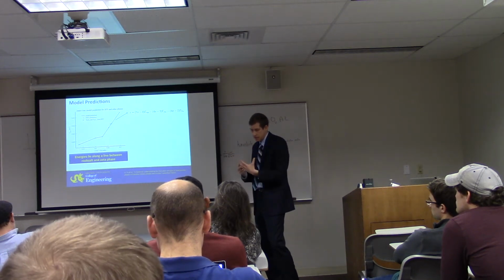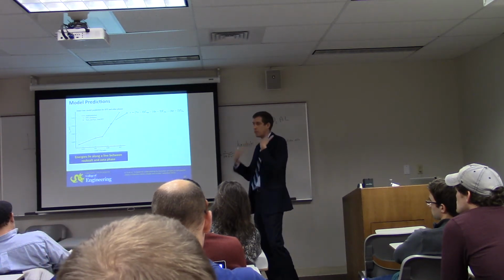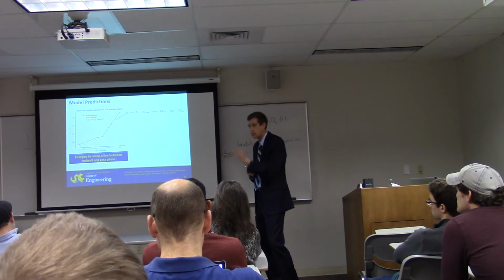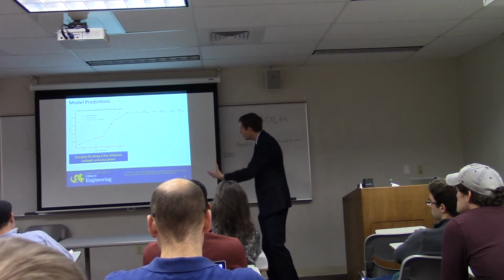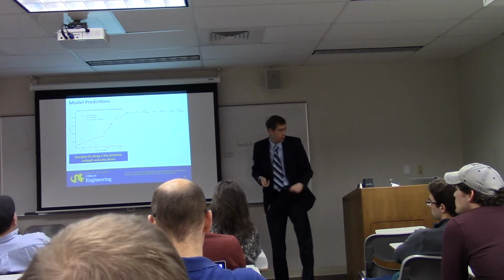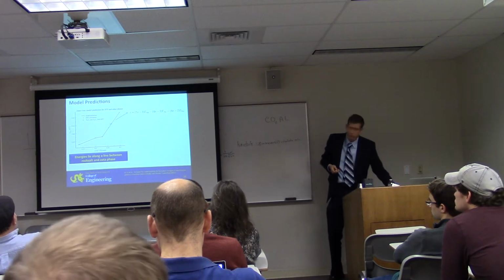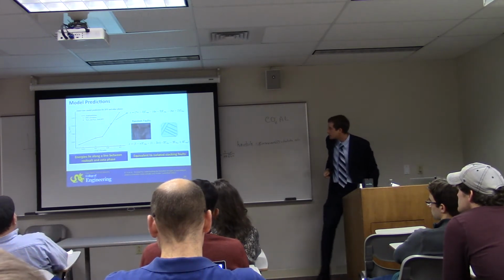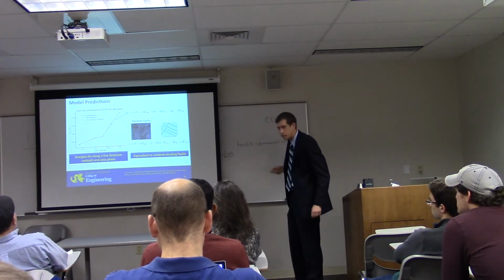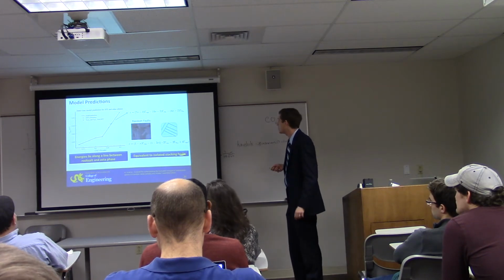And I can take it in a micromechanical model and say, okay, now I have a bunch of isolated stacking faults. I know how much that energy costs. I can do a volume average, and I can predict the cohesive energy as a function of carbon concentration and my random faults. And I come up with this equation here.